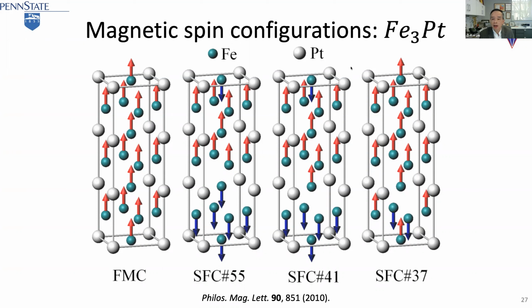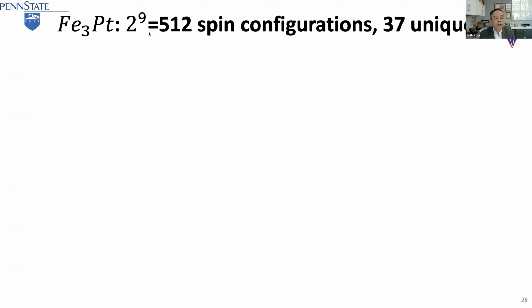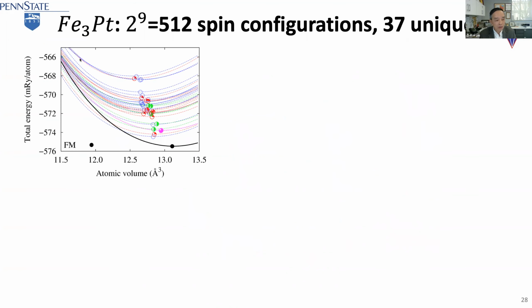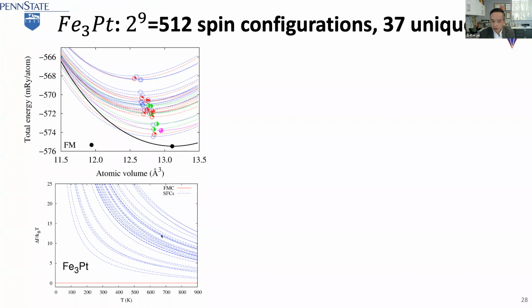It depends on how many iron atoms you have. Say you take 9 of them and take the spin configurations, you get 512 of them. But if you apply symmetry, only 37 are unique. Then you calculate all the energy from DFT at 0 Kelvin, and you can calculate all the free energy. If you know thermodynamics, you can see that at any temperature the ground state is always stable. That means from the energy point of view alone, there would be no transition. But we know that's not true because we have a magnetic transition. It's because of the competition between these.